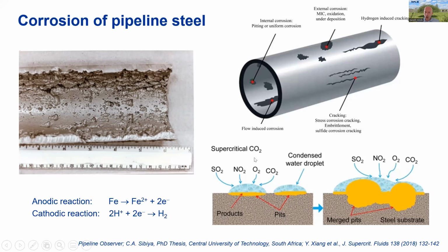Now, the mechanism of corrosion in dense phase CO2 is slightly different to that in conventional oil and gas pipelines. Here we have a dense phase with a small number of impurities. Again, Monica gave a nice introduction to where these impurities come from. These impurities tend to dissolve in any condensed water and form an acidic solution that then leads to these electrochemical reactions. And you can get then what we call pitting of the surface. These pits then join up and eventually they can lead to cracks in the presence of stress, or they can perforate through the pipeline wall over time.